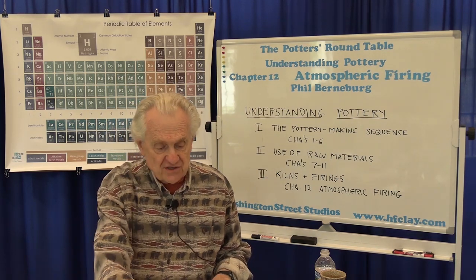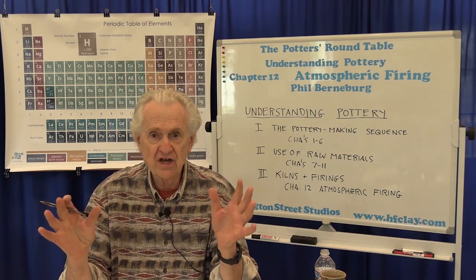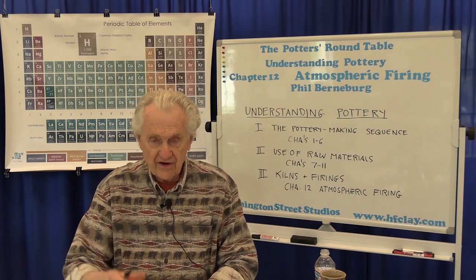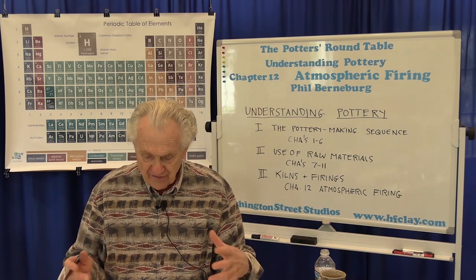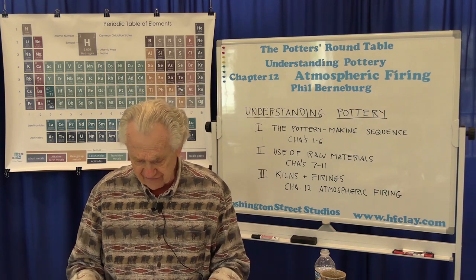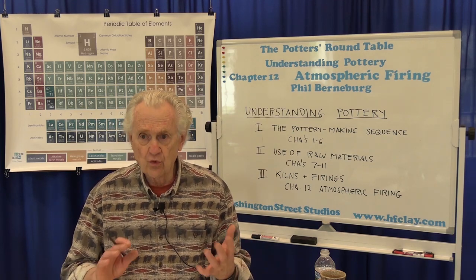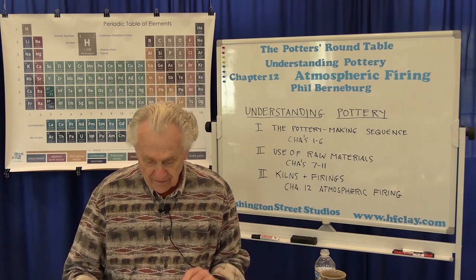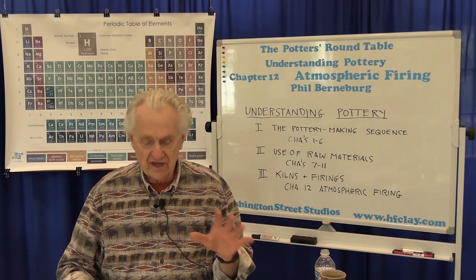There are two general features that characterize atmospheric firings. They're mostly done in reduction, and they're done at high temperatures. Secondly, there are usually additional chemical elements of some kind that are added to the atmosphere or to the gases in the kiln, and these produce new or special effects. There are really three categories of atmospheric firings: wood, salt, and soda. We're going to talk about those in order as an overview of those three techniques.